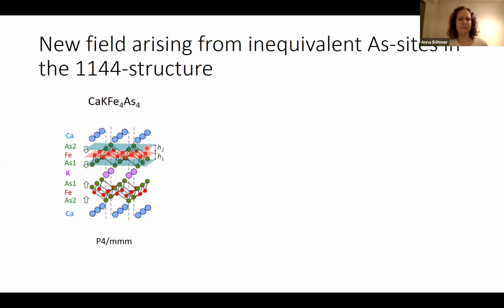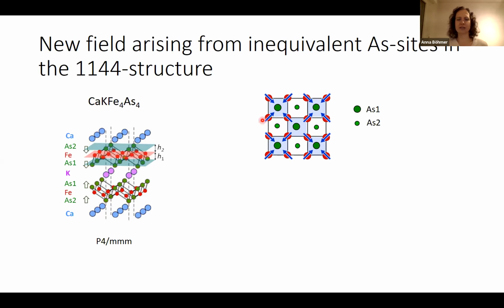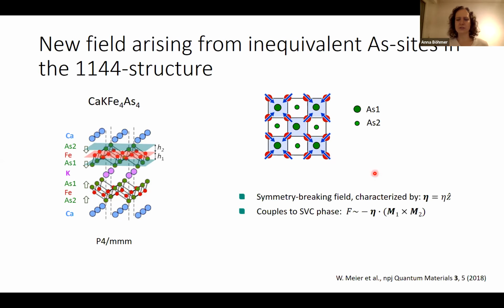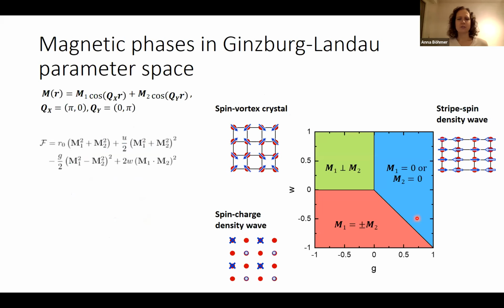If we look at this, the two distinct arsenic sites and the iron plane, I put again the magnetic structure, and now I add the arsenic atoms. They are symmetry inequivalent, they're distinct. So now this provides some sort of field. That field must be aligned along the z-axis and also has some staggered symmetry. So every other iron plaquette, there's a different arsenic site. So it really turns out that this causes a symmetry breaking field that couples bilinearly to the spin vorticity, the cross product of these two magnetic order parameters. And in consequence, I have to change my free energy expansion here.